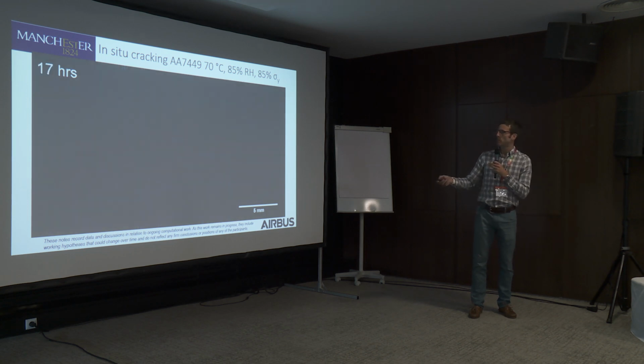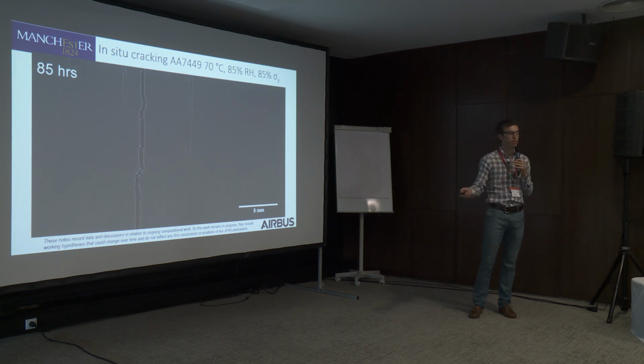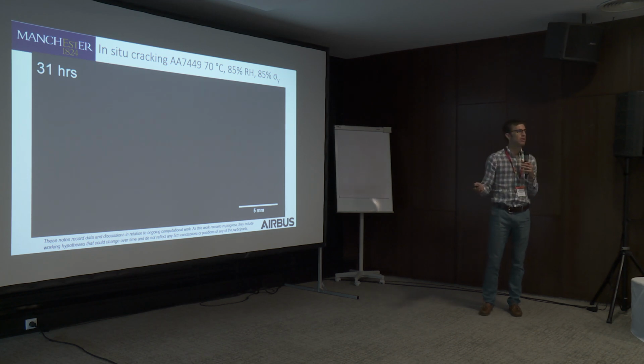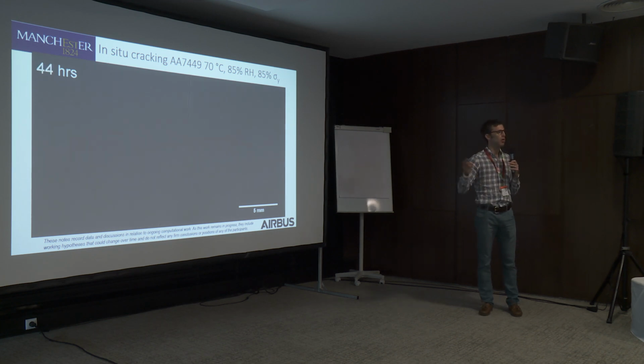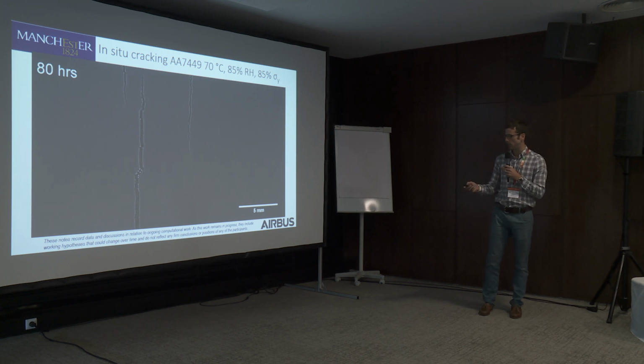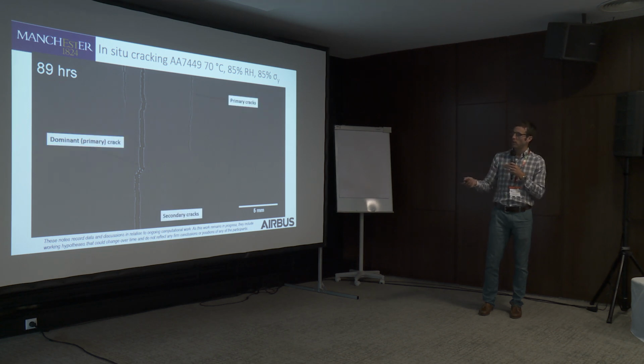Is that okay? Because you'll notice that the first crack to form is up here, but there's a crack here that joins with this one. They coalesce, and this is a sample of the crack that causes failure overall. And overall we have over 30 cracks in the total time to failure of this specimen. So this is a really neat method of finding exactly where those initiation sites are. And because it's high resolution, we can zoom right in to see where they start.